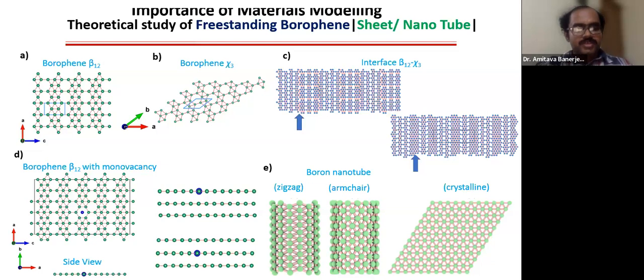Now if you have this mono vacancy, and for example you want to use this borophene as an electrode material in a battery, one of the suitable positions to fix or seed an alkali metal ion like lithium or sodium could be on the vacant site, that is, in the middle of the hexagonal hole. If you do this and stack these borophene layers, you could make a similar type of anode electrode material to what we have with graphene. And as I said in the previous slide, borophene could have greater electronic properties as compared to graphene, so that could enhance your charge density.